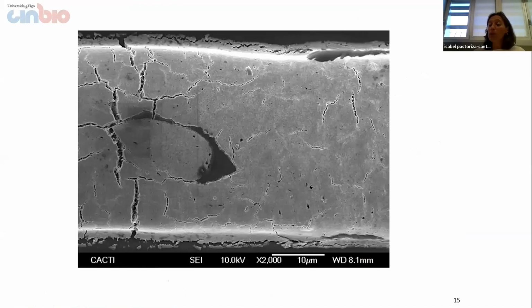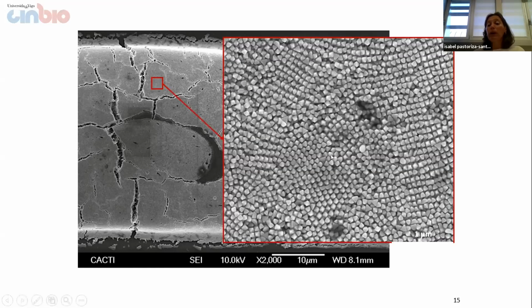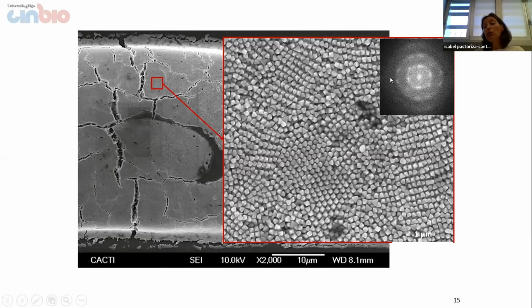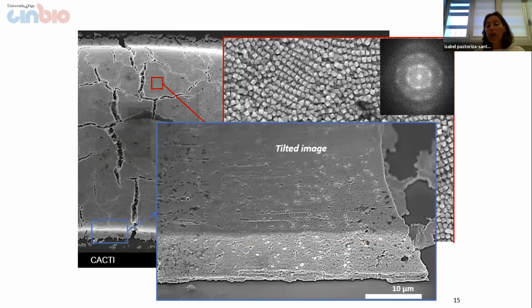So then we peel off the PDMS film in order to analyze the supercrystal, and this is a top view of the nanostructure obtained by scanning electron microscopy. If we make a zoom, we observe the nanoparticles close packed with order. Here is the fast Fourier transform, where we observe the pattern that is typical of ordered crystals. If we obtain a tilted image, we can obtain the thickness or the height of this supercrystal, which is around 10 microns, which corresponds with the height of our microchannel. So in principle, the supercrystals resemble the dimensions and the morphology of the microchannel design.